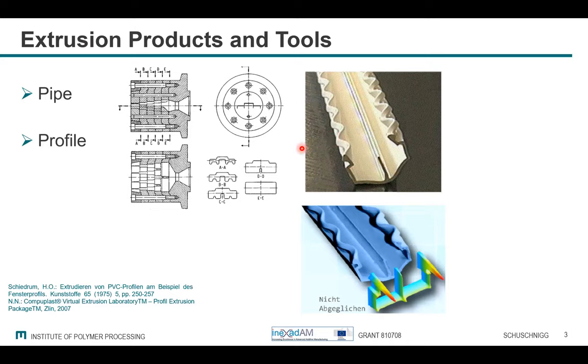After they had this problem, they went to a simulation software and they simulated the profile die. And then they saw here, this is the velocities at the outlet of the die. Overall, they have a quite good shape of the velocities, despite these spikes of the velocity. So the polymer is flowing out much quicker than the rest of the profile, and therefore it has to go somewhere. And in this case, it went wobbling around, and they could see it in reality, but also in the simulation.